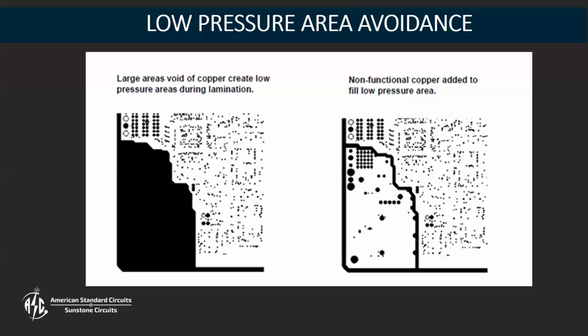So in order to fix that, you can see what they did on the right here is they added a split plane with retaining copper in that area to eliminate that low pressure area. That type of design on one layer is probably not going to be catastrophic. Probably isn't going to create too many problems, but if you stack that up, 2 or 3 layers on your 8-layer design, that could definitely create some issues with a low pressure area.